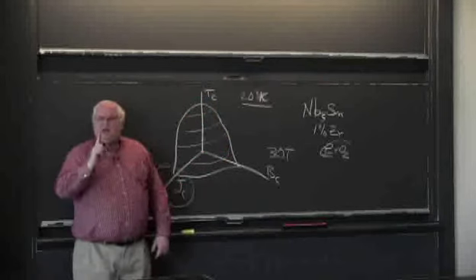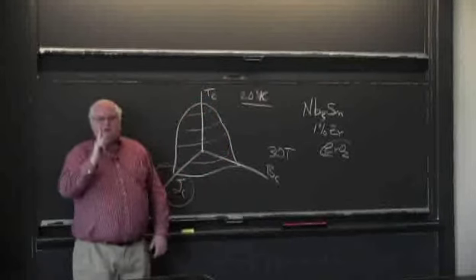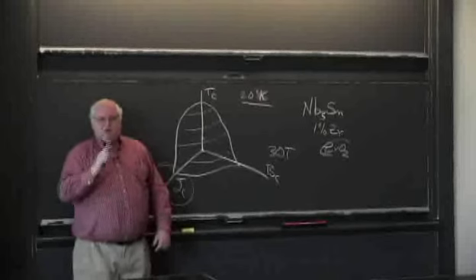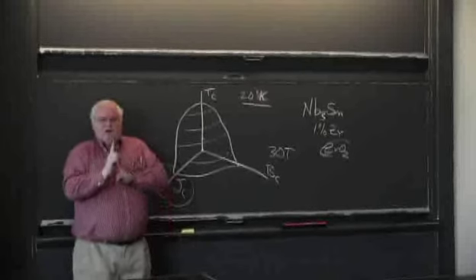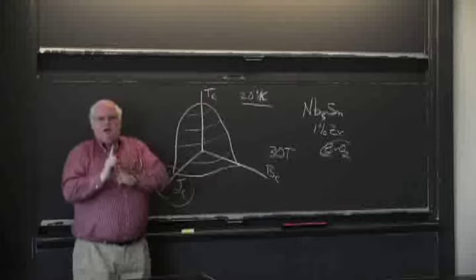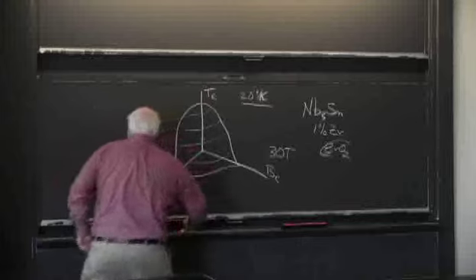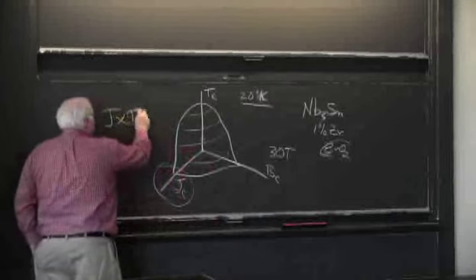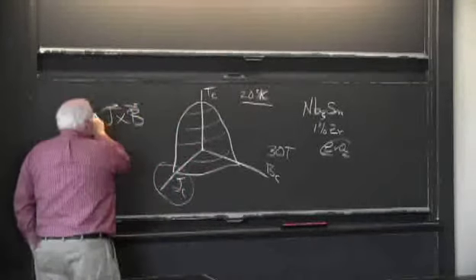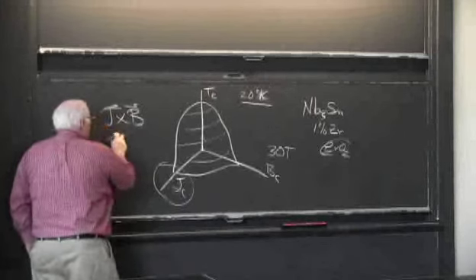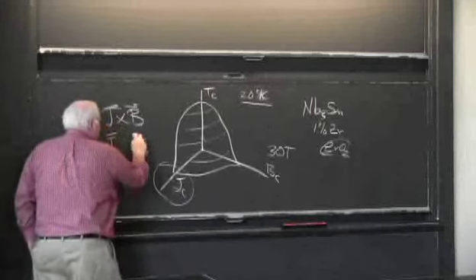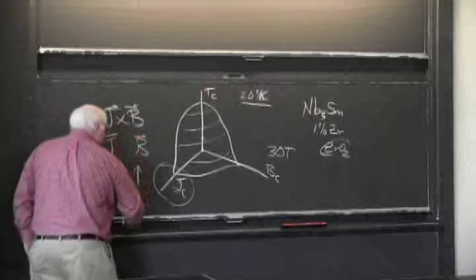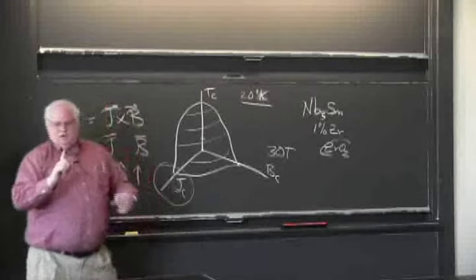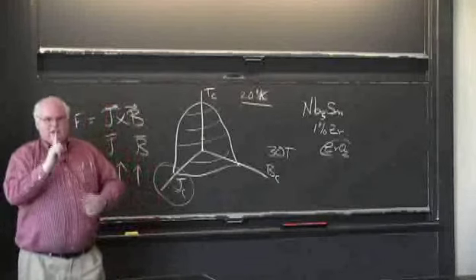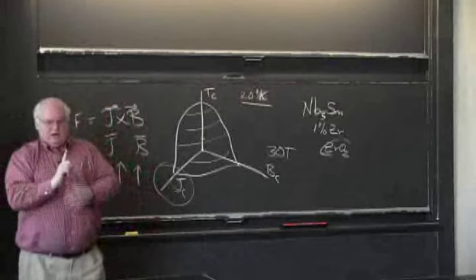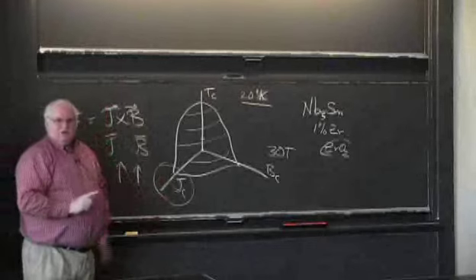One of the things that people would have laughed at me for in the 1970s is if I had published a paper where I measured the critical current with the magnetic field aligned in the same direction as the current. So it's J cross B is the force you're worried about, right? And if you want to make the force go to 0, all you have to do is have the J and the B in the same direction, right? And so you would never put your sample vertical in the axis of the magnetic field of the National Magnet Lab because there's no force trying to destroy the superconductivity.